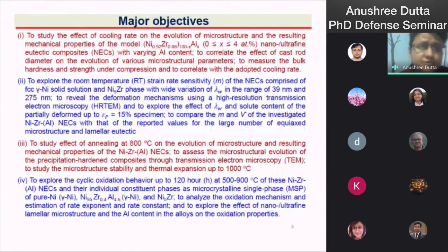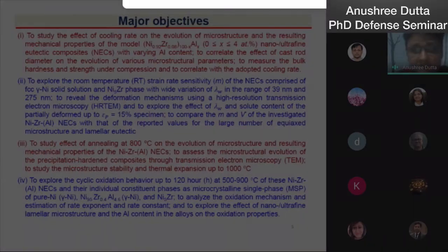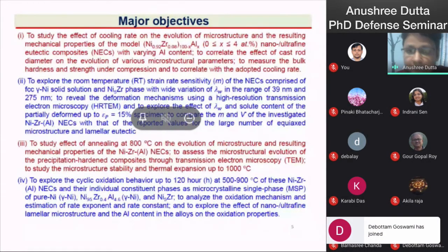The major objective of my work is to study the effect of cooling rate on the evolution of microstructure and resulting mechanical properties of these alloys, and to correlate the effect of rod diameter on the evolution of various microstructural parameters, to measure the bulk hardness and strength under compression, and correlate with the adopted cooling rate. My second objective is to explore the strain rate sensitivity and activation volume at room temperature of these alloys, with lamellar thickness varying from 39 to 275 nanometers, to reveal the deformation mechanism up to 15% plastic strain, and to compare the strain rate sensitivity and activation volume of this nickel-zirconium-aluminum NEC with other reported FCC and BCC polycrystalline alloys and eutectic alloys.